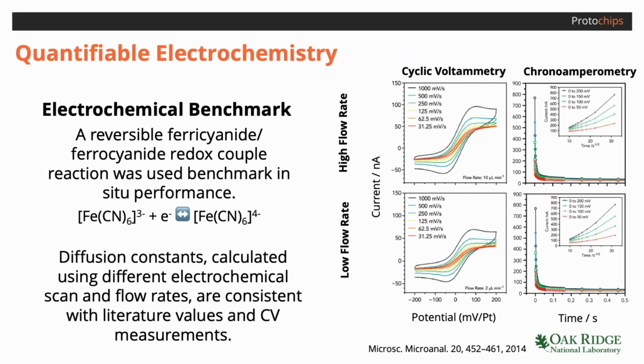A typical electrochemistry experiment, a ferricyanide-ferrocyanide redox couple, shows the sensitivity of the system. Cyclic voltammetry, or CV experiments, provide insight into mass transport and diffusion-controlled processes. These measurements, performed with the Protochips Poseidon Select, exhibited characteristic oxidation and reduction peaks when using fast scan rates due to mass transport being dominated by diffusion, while at slower scan rates, a sigmoidal profile occurred since diffusion is competitive with the timescale of the experiment.